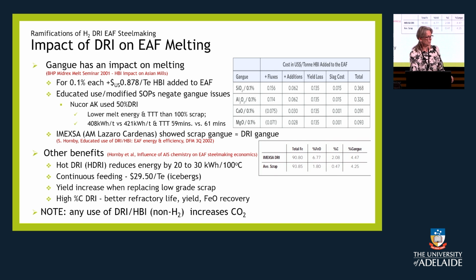There was a paper we wrote back when I was with Midrex that showed continuous feeding was worth almost $30 per ton because of the improvement in actual tap-to-tap time. And there's a yield increase when you put it in instead of low-grade scrap in some of the countries where scrap is not necessarily available. And the high percent carbon DRI is better for refractory life and yield.